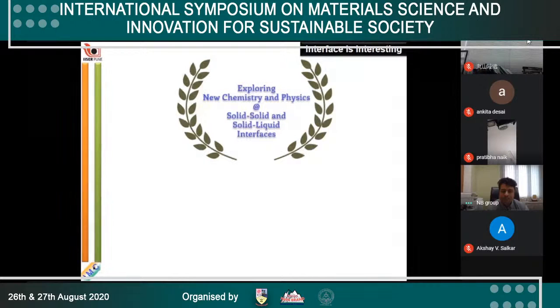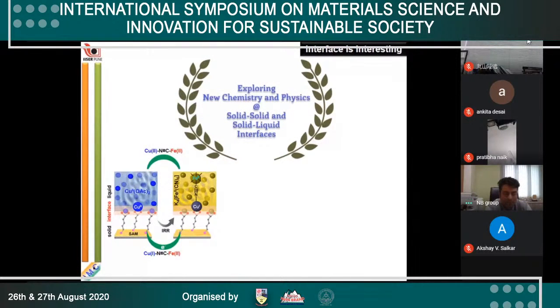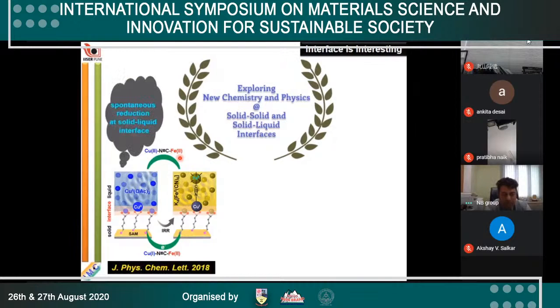Our primary objective is to explore new chemistry and physics at solid-solid and solid-liquid interfaces. Here is one example. When two liquids having copper 2 and iron 2 of such kind mix together, no electron transfer happens, and we get a solid having copper 2, CN, iron 2 coordination link. Interestingly, when we perform the same reaction at a solid-liquid interface, we get a thin film having copper 1, CN, iron 2 coordination link. Electron transfer does happen at confinement.